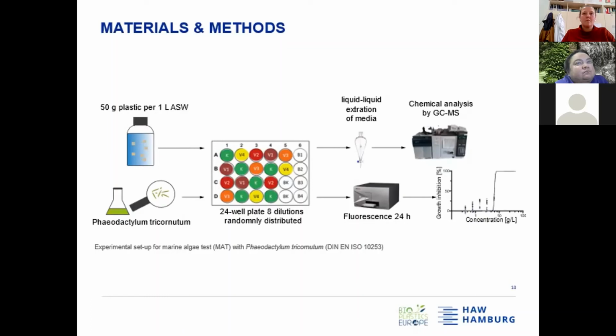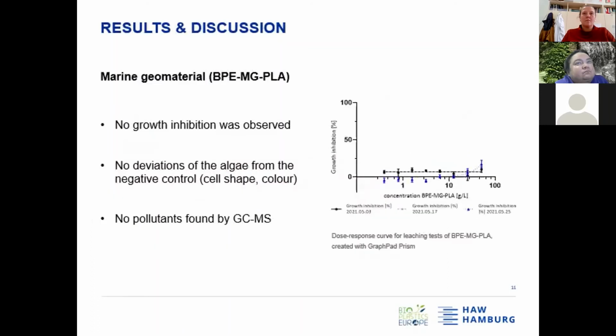So the fluorescence was observed every 24 hours. And at the end of the test, a dose-response curve for all materials was prepared, and I will explain them on the next slide. So on this slide, you can see the results for the PLA material, which should be used as Marinegeo material. And on the right, you can see the dose response curve for that material. So on the x-axis, there is the concentration of the plastic in gram per liter, and the axis is in a logarithmic scale. And on the y-axis, you can see the growth inhibition of the algae.